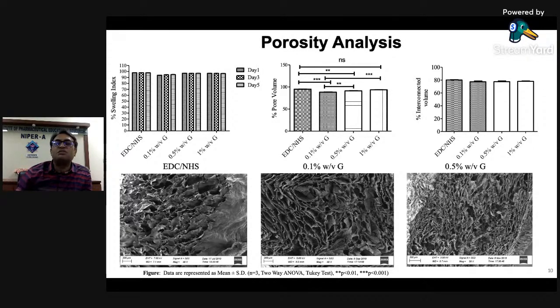There is not much difference in the porosity. However, there is definitely a certain decrease in pore volume when graphene is incorporated compared to EDC-NHS cross-linked material, which is possible because we have added another component, graphene, which is absent otherwise. So graphene has taken up some area in the hydrogel, causing a slight decrease in pore volume, which is fair enough. They all have good interconnected porosity, meaning all the pores are highly interconnected, and even the same image shows that porosity is not compromised by addition of graphene.